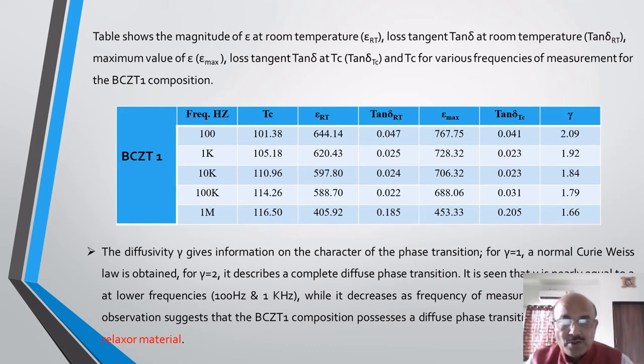Also, if we observe the variation of frequency with the dielectric constant at room temperature as well as the dielectric constant at the maximum, we observe that as the frequency increases, the dielectric constant decreases from 644.14 to 405.92 at room temperature and 767.75 to 453.33 at maximum. If we observe the values of tan delta at room temperature and at critical temperature, the values are very small, being of the order of 0.04, 0.03, 0.02 like this. That indicates that this composition has very small losses.